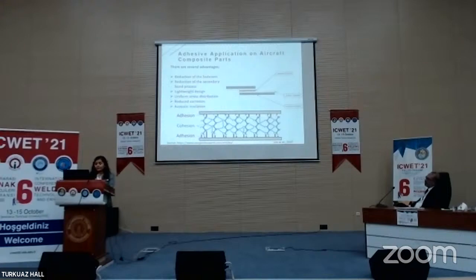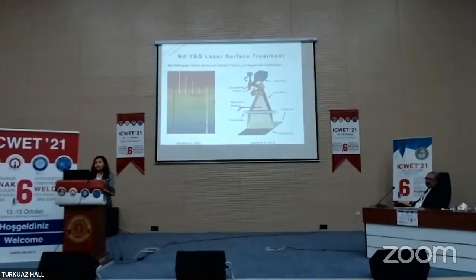However, the main disadvantage of adhesive bonding is that bonding strength is determined by the type and the surface condition of adhesive and adherent. Moreover, polymer matrix composite exhibits low surface free energy, which causes poor adhesion on the surface. To achieve durable adhesion on the composite surfaces, pre-treatment is needed to modify surface wettability and morphology, and remove surface contaminants. Nd:YAG laser irradiation presents a new technology for surface treatment and surface modification of various adherent materials. This technology offers an alternative to ecologically unfriendly chemicals involved in conventional etching and abrasive treatments.